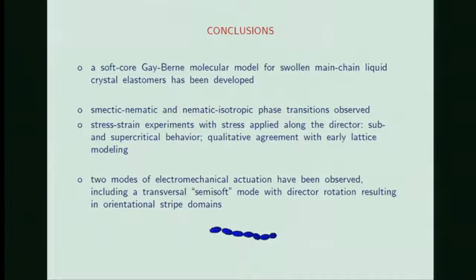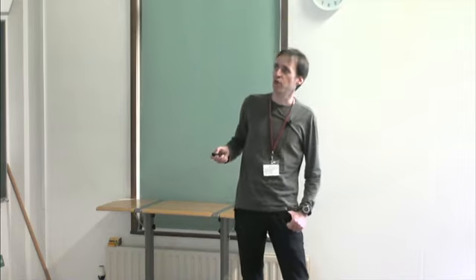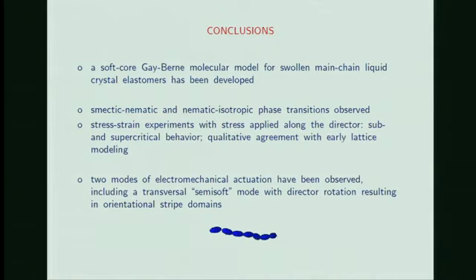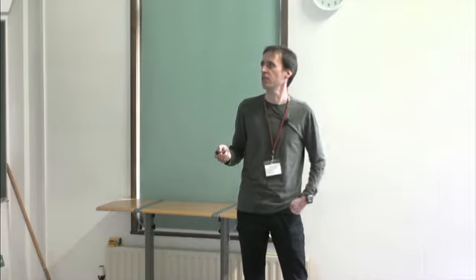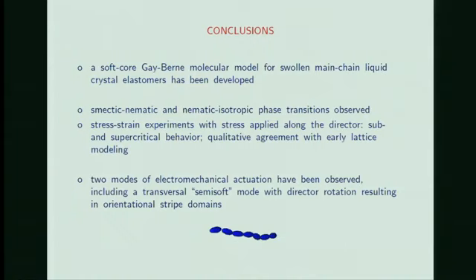Okay, now to conclude, what we had here was a soft-core Gay-Berne molecular model for swollen main chain elastomers. We have smectic, nematic, isotropic transitions, and some simple stress-strain experiments with stress aligned along the director. We have the supercritical and subcritical behavior, which qualitatively agrees with this early lattice modeling, and also with the phenomenological picture of this mechanical field. Then we had a look at two modes of electromechanical actuation, including this so-called semi-soft geometry, where the field is applied perpendicular to the director. We have this direct rotation now, and the stripe domains that can be observed in our system.